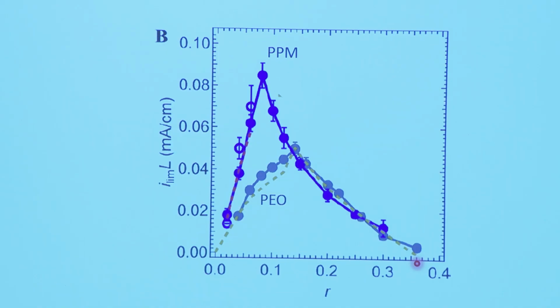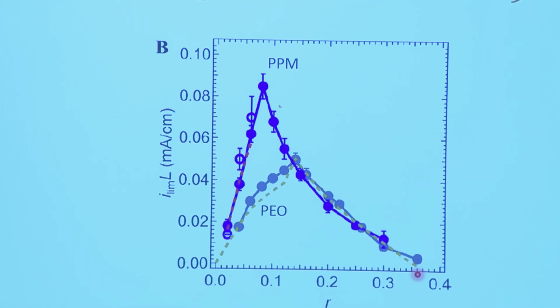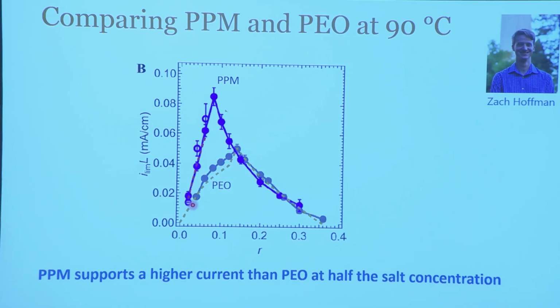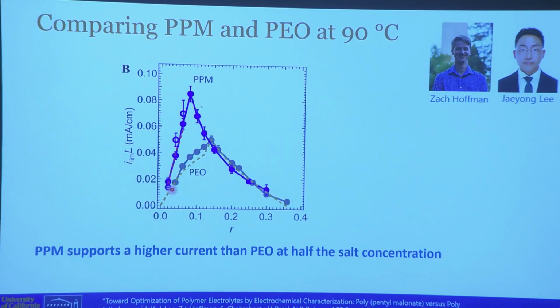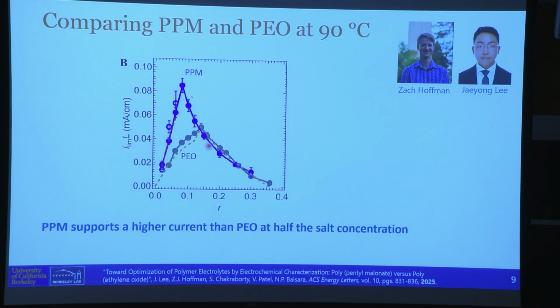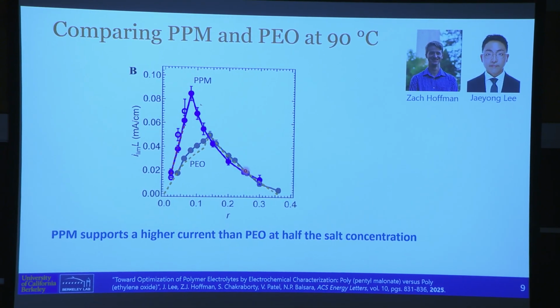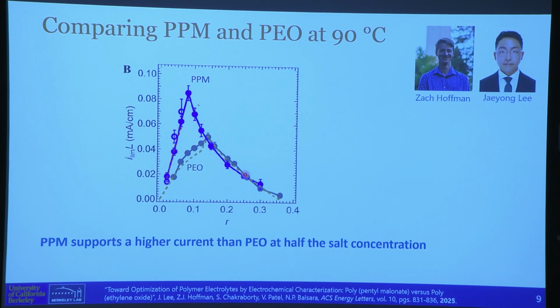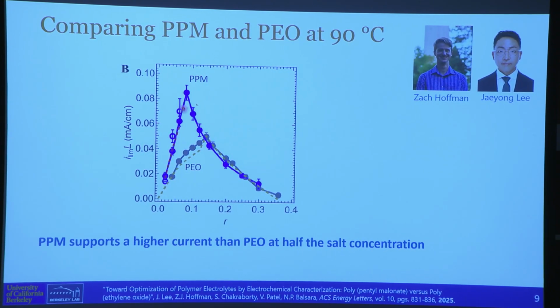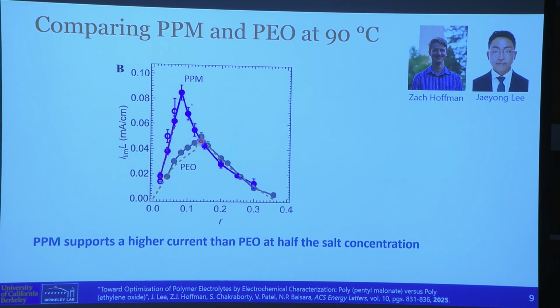And I think it is because PEO is very easy to work with, and PPM is also easy to work with. So as you increase concentration, the current you can hold is large, and it increases because you have more and more charge carriers. But at higher concentrations, friction takes over, your transport goes to pot, and your limiting current goes down. And PPM has about twice the limiting current of PEO. Okay. I would claim that PPM is the best polymer electrolyte known to man. I would also love to be shown another electrolyte that is better. Okay. It also supports that at half the salt concentration. And that's also valuable because salt turns out to be the most expensive component of the battery, actually.